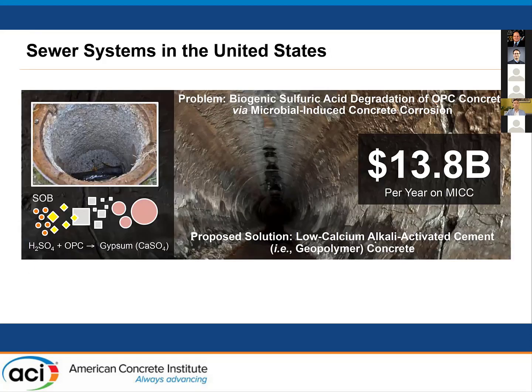Our primary goal, of course, is to solve the problem of biogenic sulfuric acid degradation of ordinary Portland cement concrete. So we've heard a lot about this problem from the previous two speakers. What I do want to point out here, in the lower left-hand corner, in terms of the mechanism, is that the sulfate-reducing bacteria in the wastewater produce this hydrogen sulfide gas. The acidophilic bacteria, really the sulfur oxidizing bacteria, convert that H2S into sulfuric acid. The sulfuric acid can react with the calcium-rich phases in ordinary Portland cement, like calcium hydroxide, and the acidic environment leads to decalcification and the degradation of calcium silicate hydrate. And that really is the cause of that gypsiferous layer that we see that can form on the crowns of sewers. It's really quite weak and quite friable.